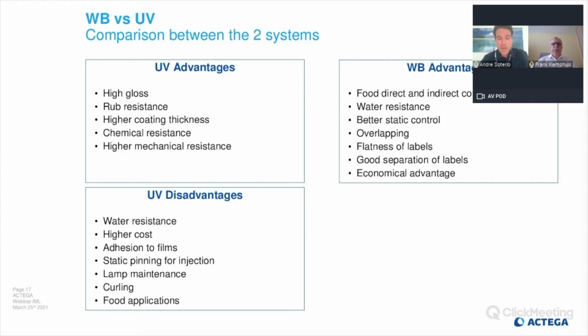If we look at water-based products, we have a lot of advantages. As I said, one of them is direct food contact and indirect food contact. Water-based are much easier to control for that usage. The other one is the water resistance. Although it's, as Frank said, diluted in water, as soon as this water is gone and you have a very nice dried polymer film, it has most of the time an excellent water resistance.